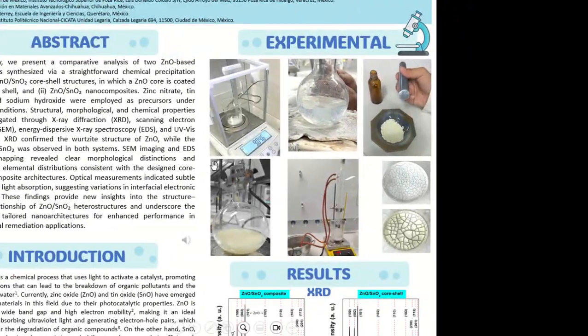Experimental details. For the synthesis of zinc oxide in a core shell with tin oxide, the zinc oxide synthesis was first carried out as follows. 9 grams of zinc nitrate were dissolved in 100 milliliters of water, and a sodium hydroxide solution, 6 grams in 100 milliliters, was added dropwise, and the mixture was left stirring for 2 hours. The precipitate was washed either by decantation or centrifugation with water, and dried at 120 degrees Celsius overnight. Then, the tin oxide shell was prepared.